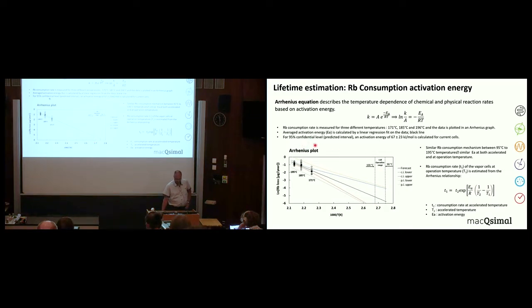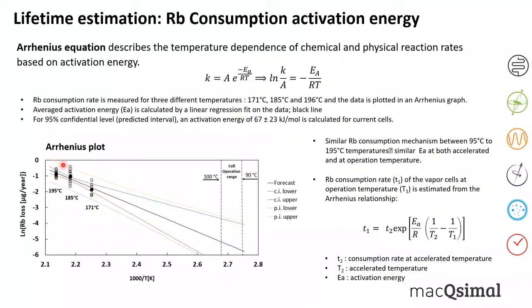But with this, we could extract the activation energy of these processes of rubidium disappearing of 67 kilojoule per mole and a huge error of 23 kilojoule, which is related to the fact that we have all the measurements here. Why we do the measurements here at 195 degrees, it takes roughly some months.